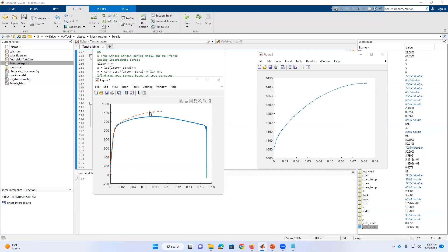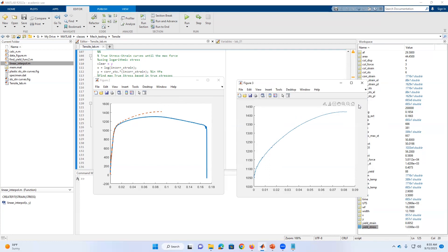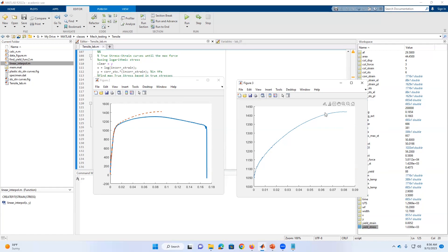That's why we plot the true stress-strain curve only up to the point of maximum stress. In this section I'm plotting the data — we have two plots. The first plot shows the engineering stress-strain curve as a solid line and the true stress-strain curve as a dashed line. Figure 3 shows the plastic strain: the same curve but with the elastic part removed and normalized to zero, starting the plastic strain curve. This is important for modeling purposes — for example, for a Johnson-Cook model, you just want the plastic side.